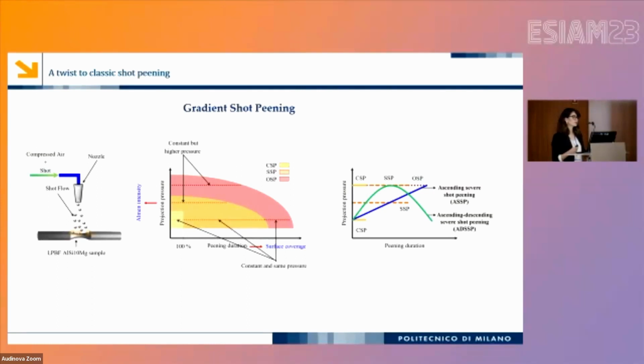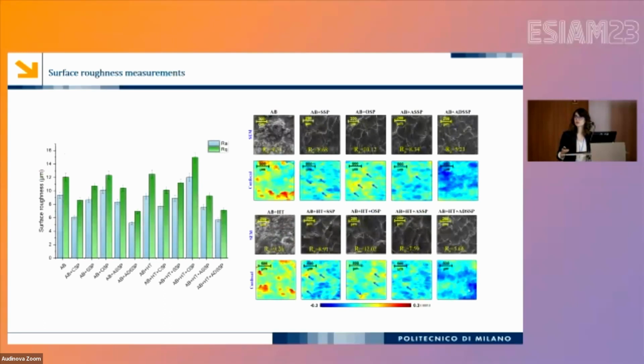And in this way, we wanted to modulate the surface roughness as we are performing the process of shot peening. The results here were very interesting because with the ascending-descending shot peening especially, we were able to reduce considerably the surface roughness with respect to the other treatments, while maintaining the compressive residual stresses and all the other positive effects of the shot peening treatment.